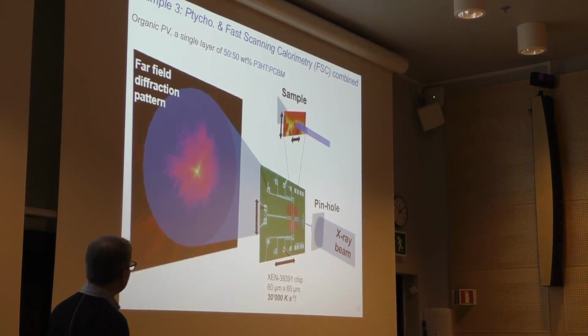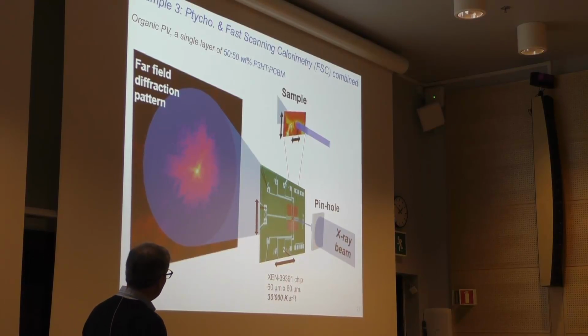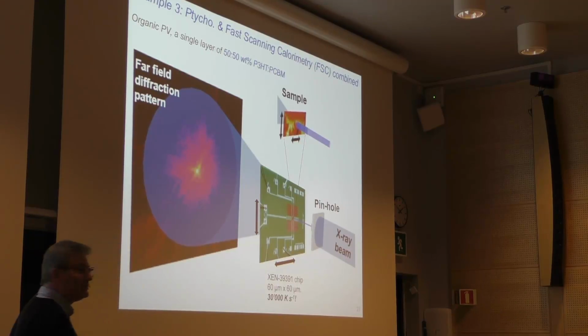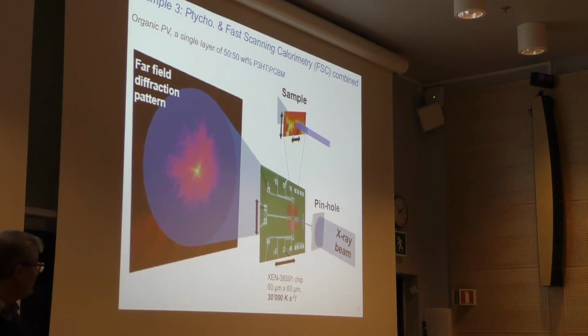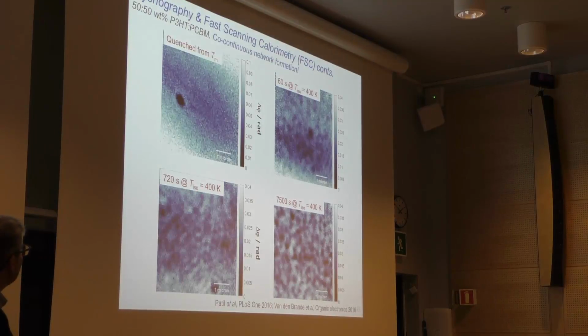extremely quickly. So here's again a close-up of what is going on, that we have the silicon nitride window with the organic film deposited on top of it, and by shifting the sample around, we can look at the structures that we see on this silicon nitride window.